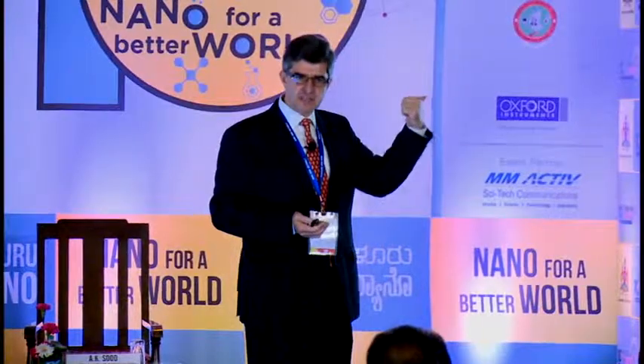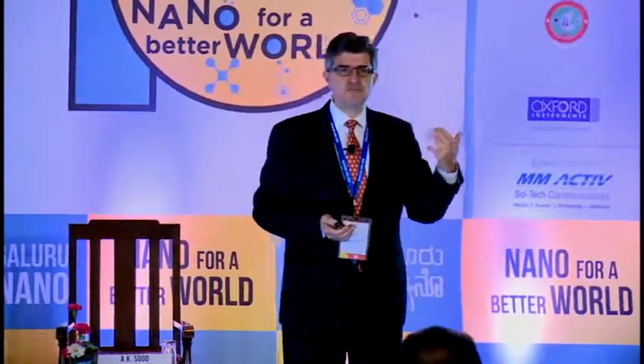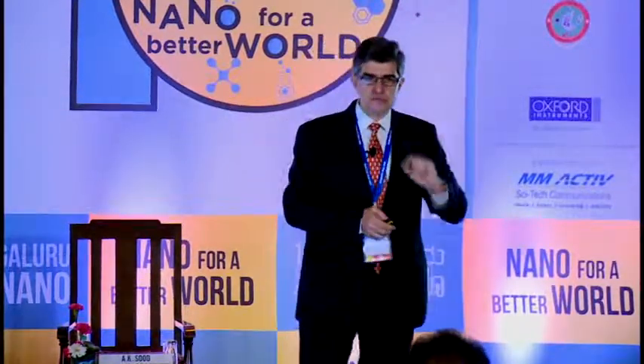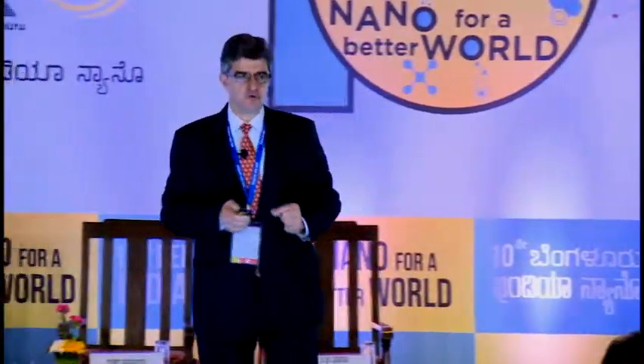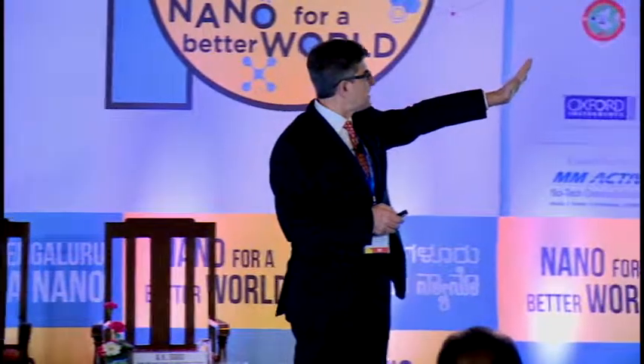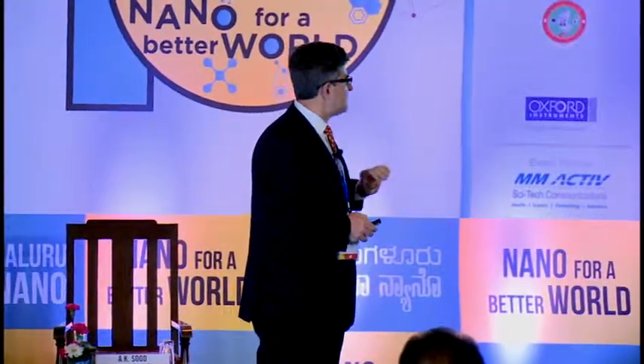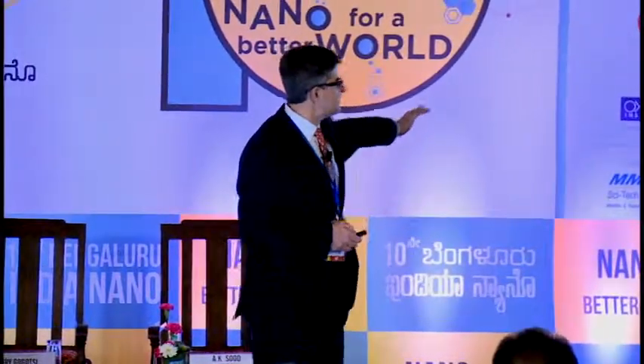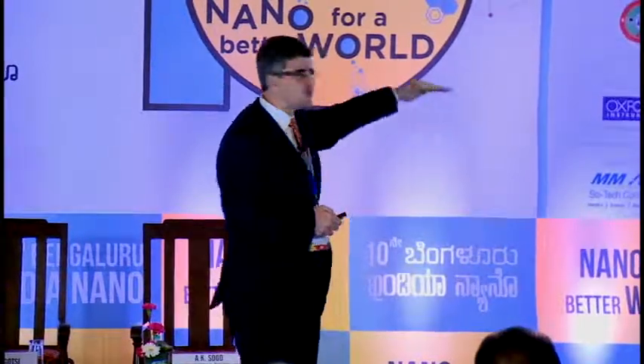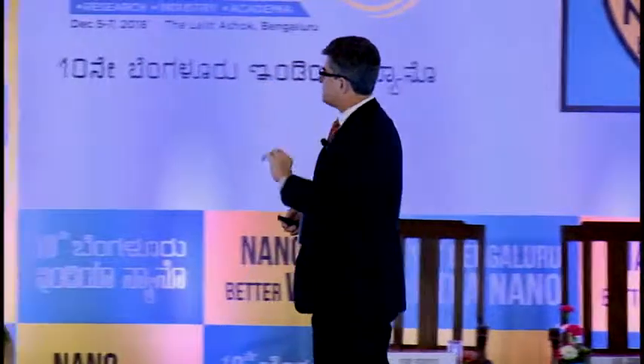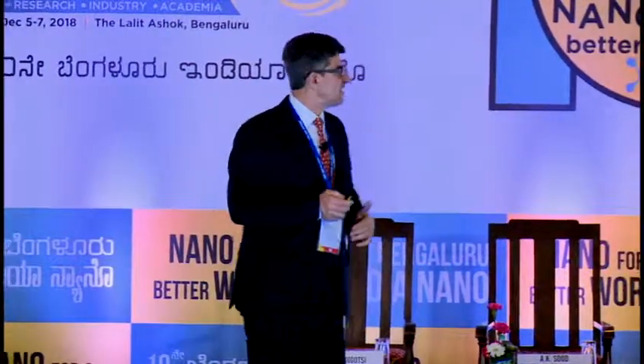Moreover, we can push them in another application I'm not going to talk about today, even toward electrolytic capacitor rate, because of their conductivity, we can go to the range where we can do AC-DC conversion of the current. But we basically can combine battery behavior, those are the right plots, and supercapacitor behavior in one material. Because again, we have layers where electrons can run within layers and ions can move between layers. What I'm showing here, for example, is a structure of titanium carbide Ti3C2 MXene with a monolayer of water, and water with potassium ions or sodium ions in between. But it's important that it can be small ions like proton and lithium, but even large magnesium 2+ and aluminum 3+ can still be intercalated, spontaneously or by applying charge.